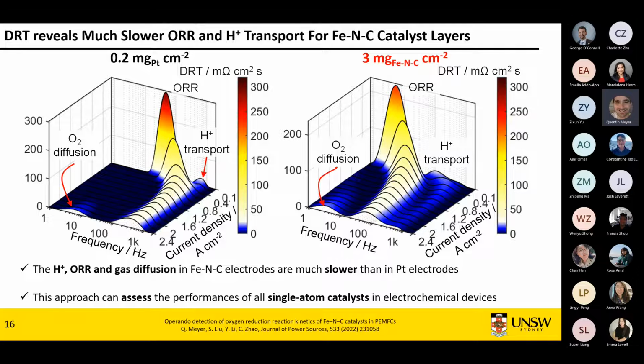So this approach is actually good to assess performance of single atom catalysts. And this extends to even other types of catalysts and works well in any type of electrochemical devices. You don't need to have a very fancy model. You just capture your process, and you should be able to capture. You should always obtain similar things regardless of the material, but the way the peaks are distributed and the frequency they are at is directly caused by your material properties, basically.